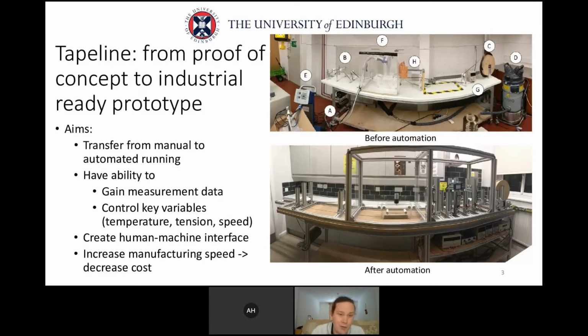So the history of the tapeline has been taken along 4 to 5 years. So it's coming from a European project called Marine Camp, in which we built the original tapeline, as you can see on the upper photo here, and that was basically a proof of concept where we already had a lot of good ideas, such as using an electrostatic powder gun and a Joule heating system in order to create tape. But by then we had little control on tension, temperature, speed.